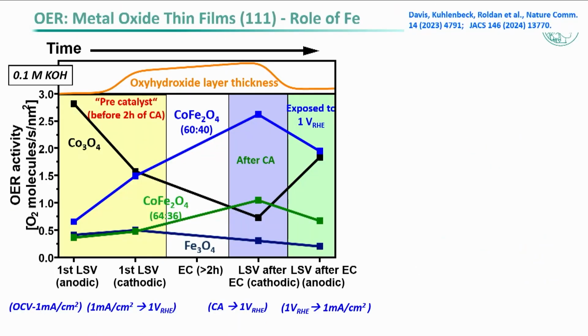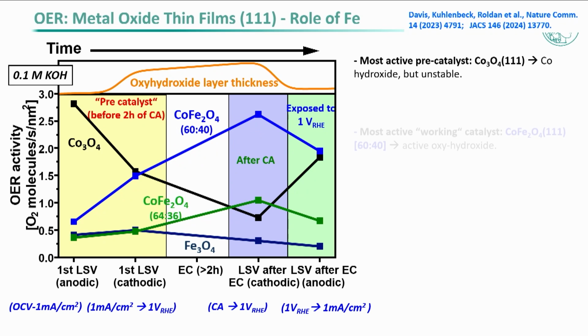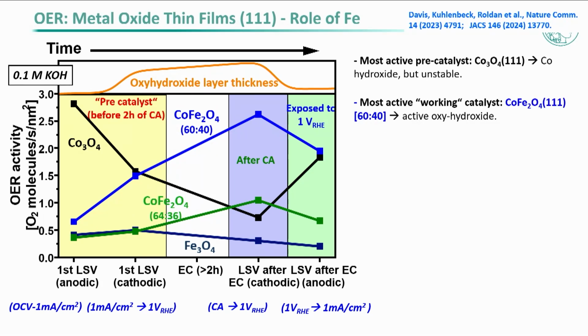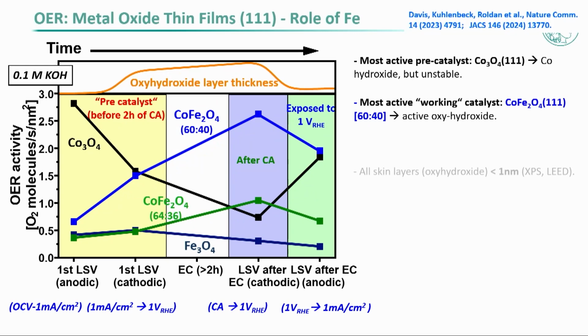And within these thin films, we can be very quantitative. So we can look at how much oxygen we are producing, and we can look under reaction conditions, and we can look at the beginning. And again, at the beginning, we have the cobalt oxide more active than the cobalt iron oxide and the iron oxide. But under the reaction, after the material has changed and became in the active state, then the cobalt iron oxide is the most active working catalyst. It has the most active oxyhydroxide.